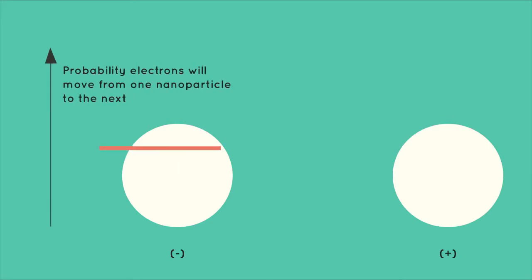The reason is an effect called quantum tunneling. To understand it, we need to think of electrons not as particles, but rather as waves. Doing the maths behind this shows us that in order for electrons to move from one position to the next, they always have a certain probability. And the probability of going through the polymer is non-zero; it is just reduced exponentially with increasing barrier width.